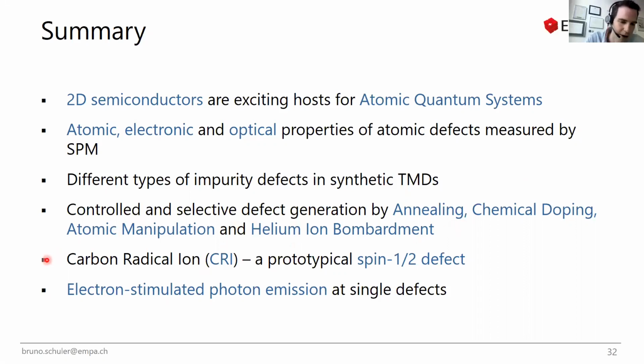Then we identified an interesting, very prototypical spin 1/2 defect, which is what we call a carbon radical ion, that we can generate also selectively. And we looked some more into the optical properties of single defects.